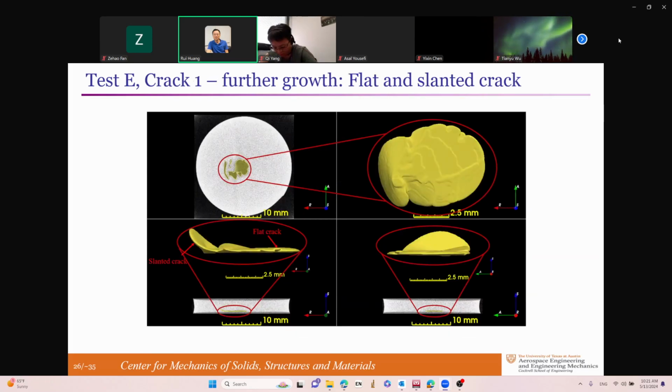All right. When the crack grows at an angle first, it reaches the interface, but doesn't penetrate the interface. I don't know if you can see it on the screen, but it's a crack that's parallel to the interface, but distinctly separated from the interface. So it moves along at an angle, comes parallel to the interface and continues along as a very highly mixed mode crack with the attendant twisting, cracks, fragmentation, and things like that.